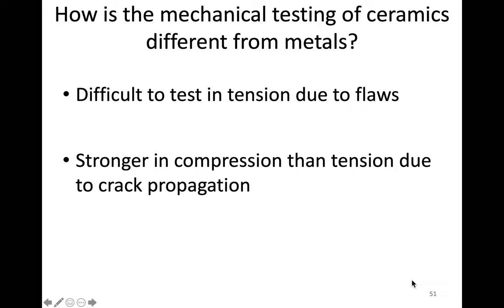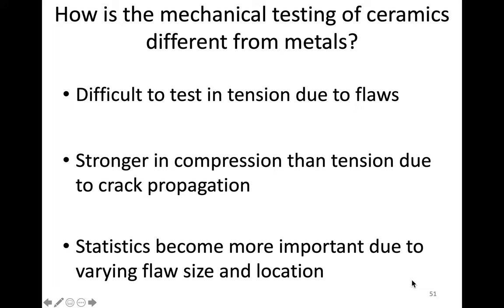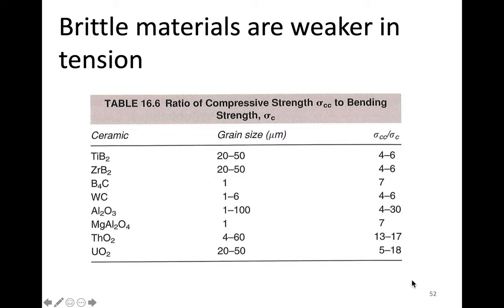These flaws result in materials stronger in compression than tension due to crack propagation. Because of this difficulty in testing and the fact that they're stronger in compression, the strength will vary depending on flaw size and location, so statistics become much more important in these materials.